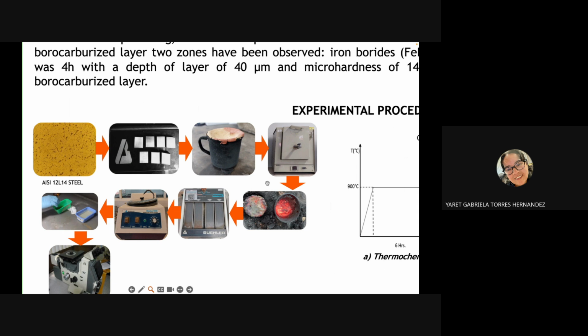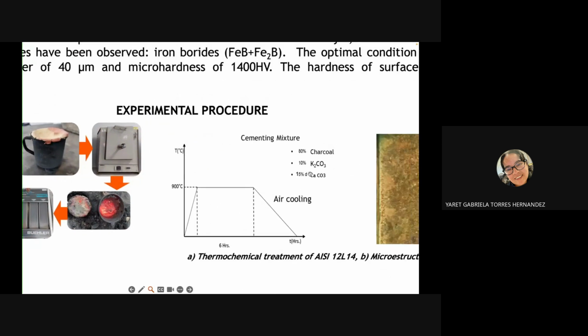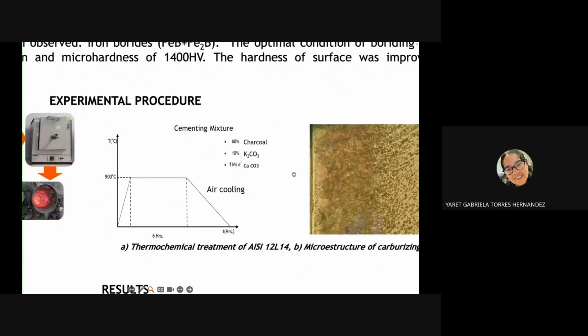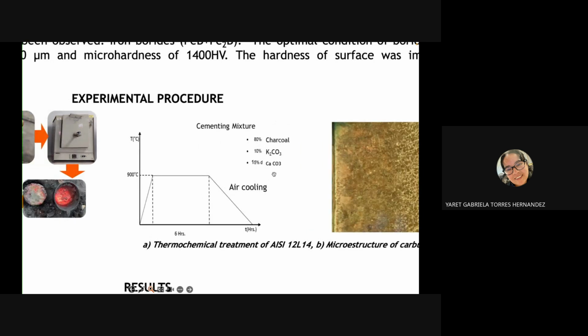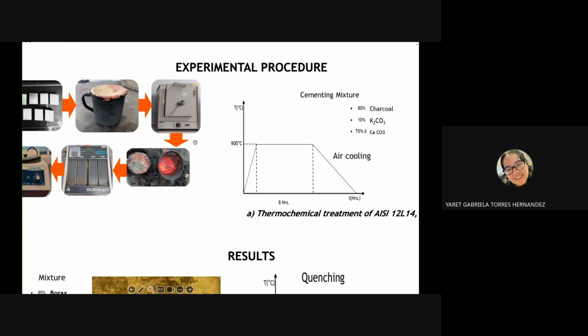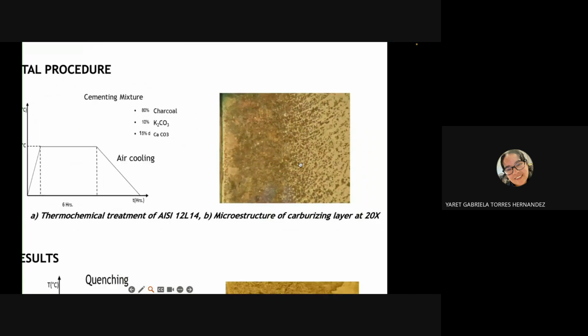First, the samples were cut into cubic bars and cleaned, and then the pack carburizing was carried out by embedding the samples in a closed container containing a cementing mixture with 80% charcoal, 10% potassium carbonate, and 15% calcium carbonate. The container was placed in a conventional furnace for 6 hours, followed by air cooling. The carburized layers show pearlite,